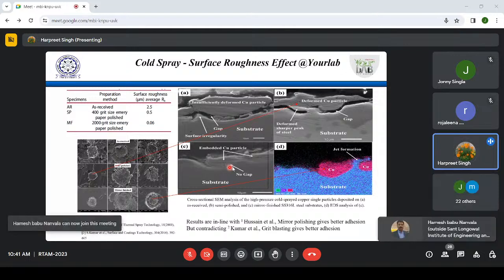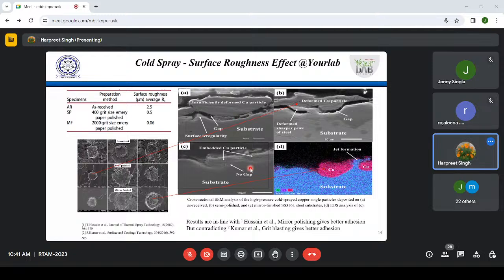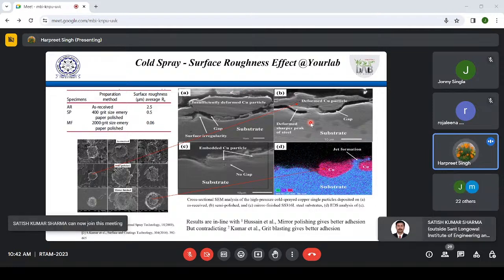level. But you will see in the literature, there are certain other combinations where the surface roughness is helping. Our understanding mainly comes from the fact that if the substrate material is very hard or has enough strength that these peaks are not getting deformed, then probably surface roughness can help. Why? Because imagine if this had not deformed, it would have stayed in its straight position, and the particle would have deformed over it, and good adhesion would have been achieved. So probably where we have a hard surface and a slightly ductile coating material, the surface roughness is helping.